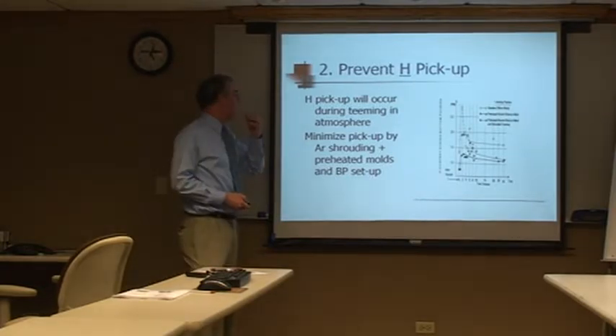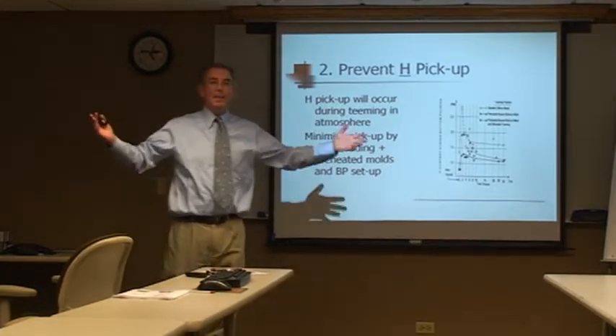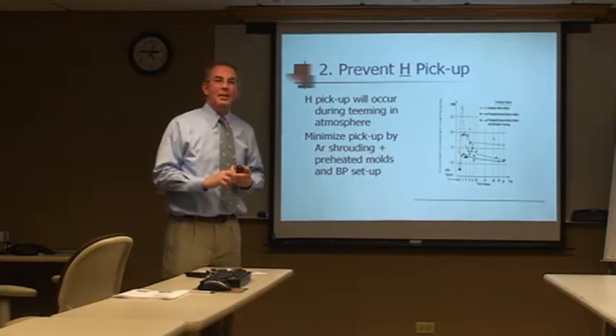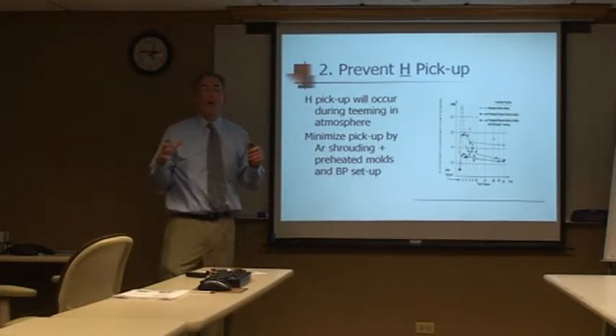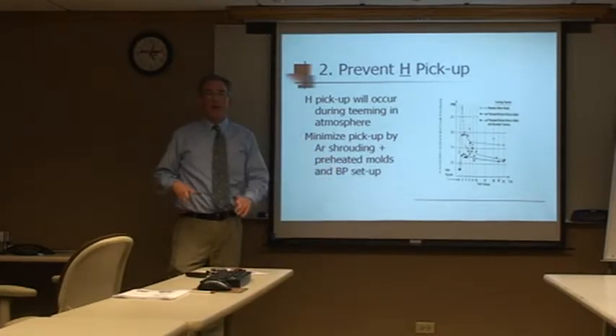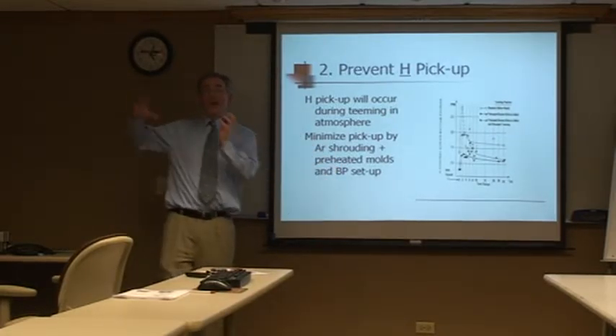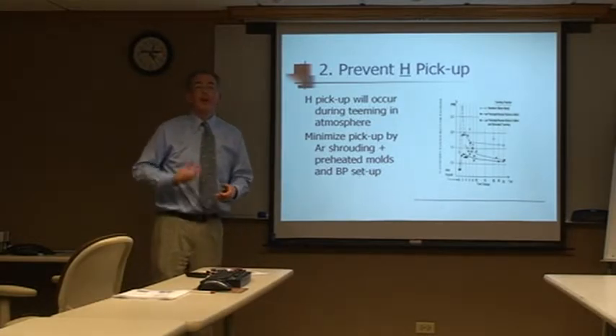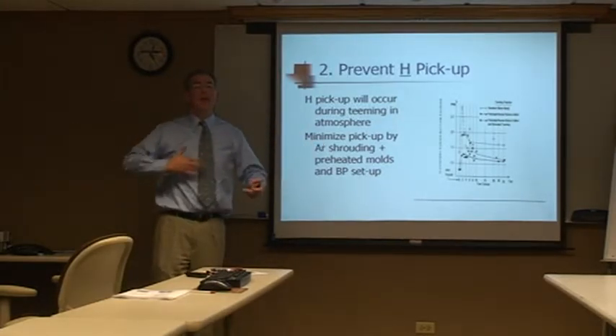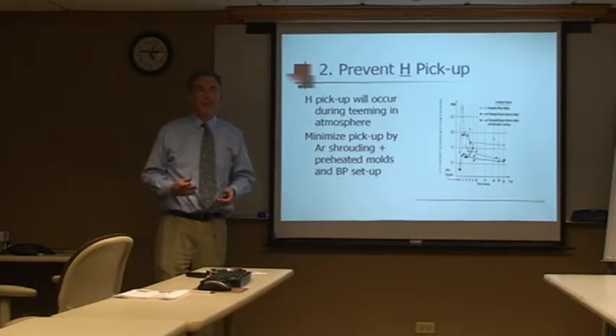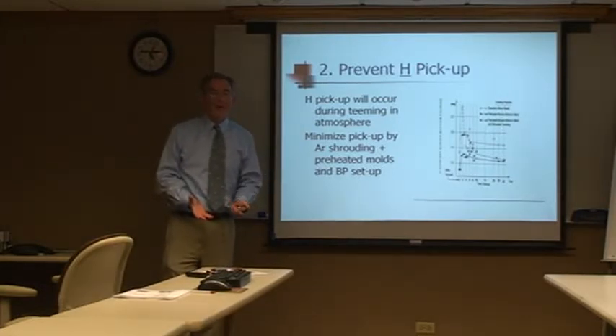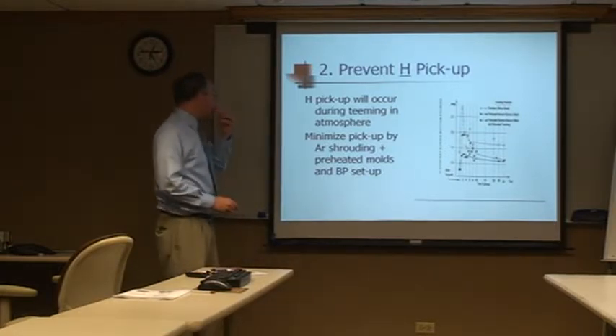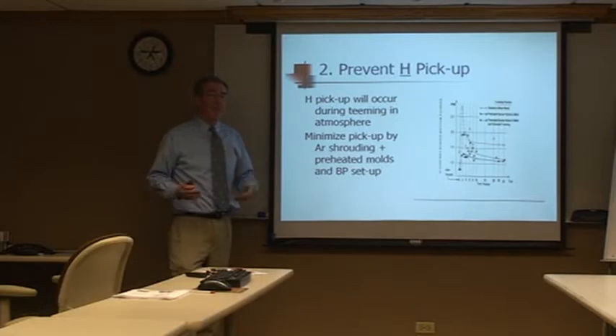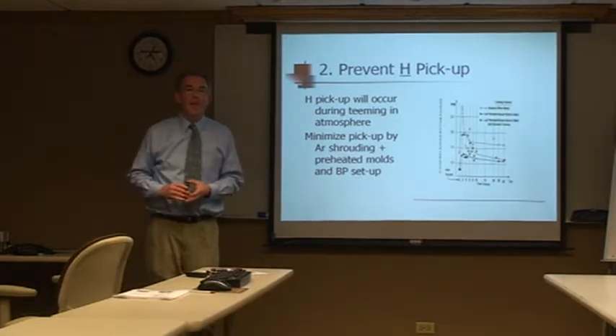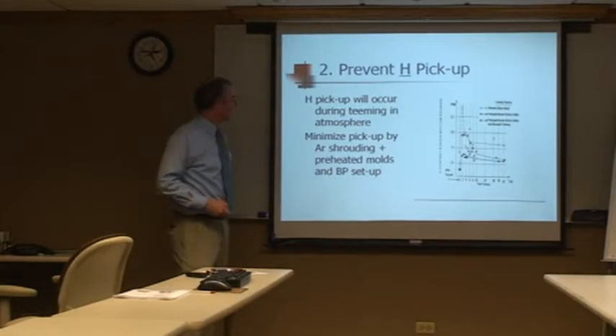We want to prevent hydrogen pickup. When we teem, we're teeming in air, and there's moisture in air. We need to preheat the molds. We have a lot of heat. So what an enemy is condensation. So rather than pouring cold molds, we will actually preheat the molds before we bring them into service. And then once they're in service, they're in a hot environment, so there's natural high level of heat to prevent condensation. But a little bit of condensation on a mold is a hydrogen pickup. We also use an argon shroud, which helps us guard against maybe about 1/10 of a ppm pickup during teeming as well. So those are two important parts.